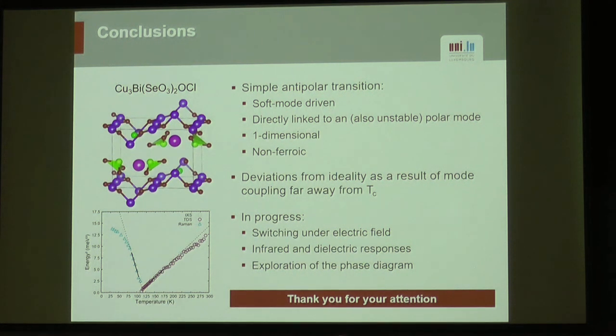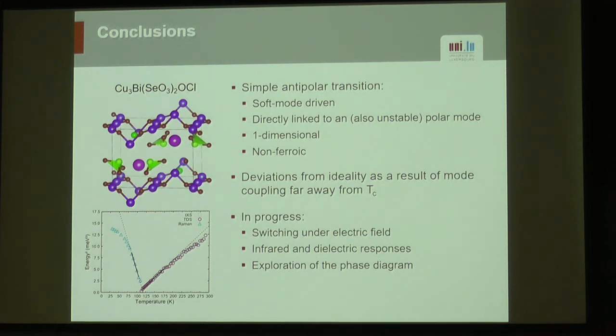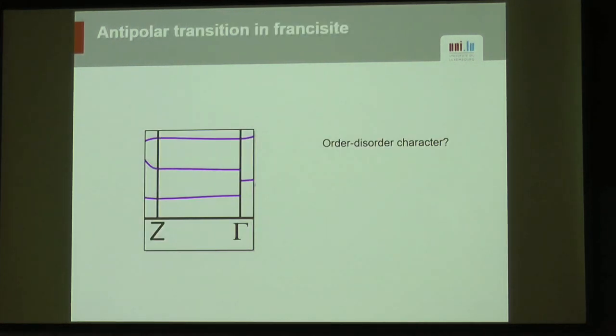Is it known how the soft mode will change if you change the halogen, from calculation? From the calculation, yes, it's known in this paper by Prishchenko. Essentially, what they find is that if you go to bromine, it is still slightly unstable, but less than chlorine. But still, experimentally, there is no phase transition. And if you go to iodine, then it's completely stable. It's completely stable. Yes. I see. Okay.